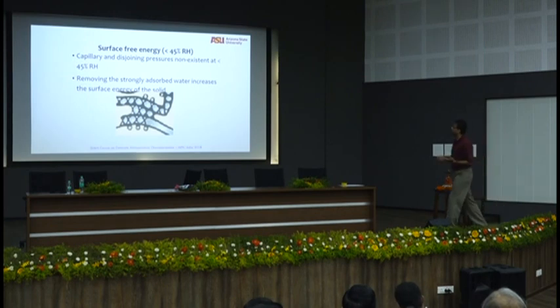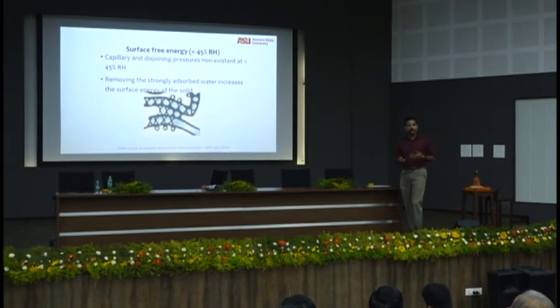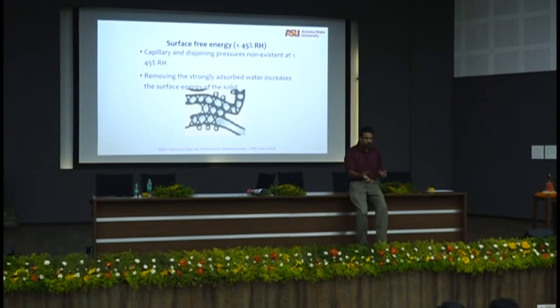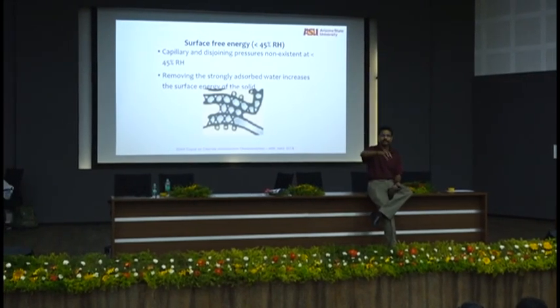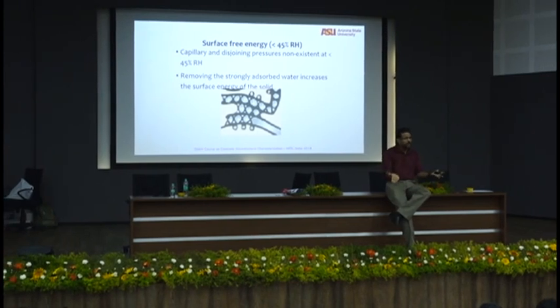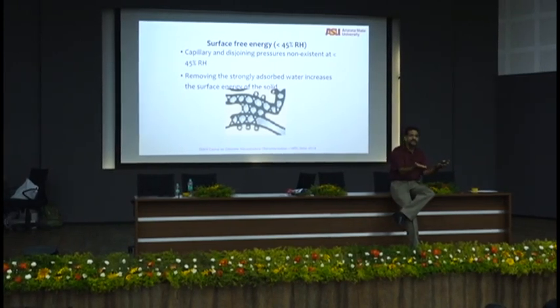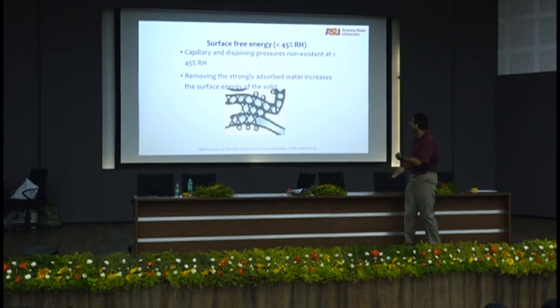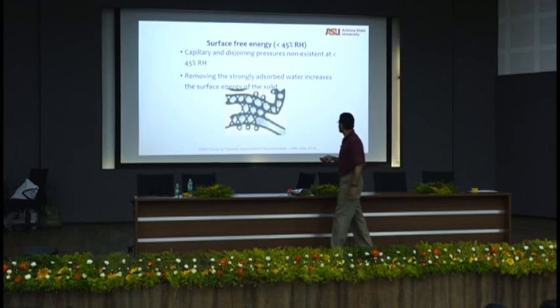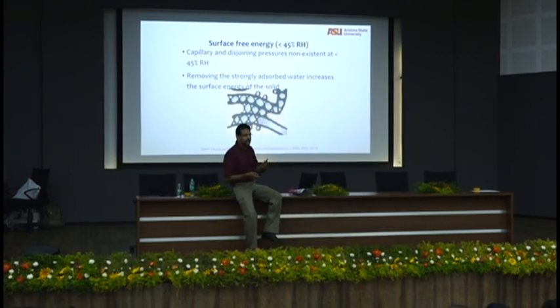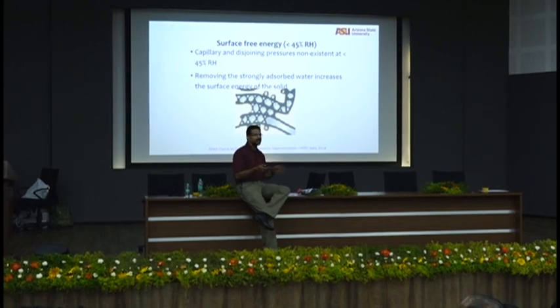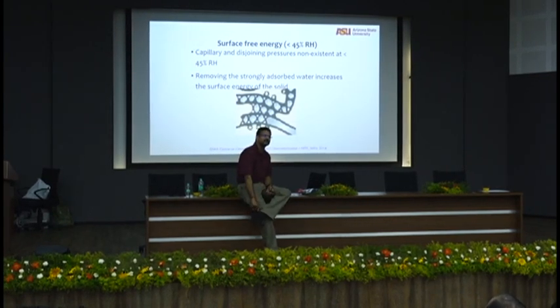So removing the strongly adsorbed water increases the surface energy of the solid. When I remove a layer of water, you remember BET theory, nitrogen forming layers on the surface, right? When you start to remove that, you have to overcome the surface energy of the solid. So a lot of pressure is created, and that happens at low RH. You really don't see it unless it's very, very dry. Where I am in Phoenix, we have a lot of surface energy effects, but in most places with a reasonable amount of moisture saturation, capillary and disjoining pressure is enough to talk about shrinkage.